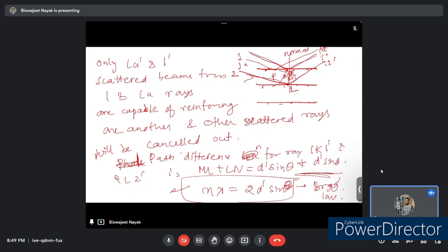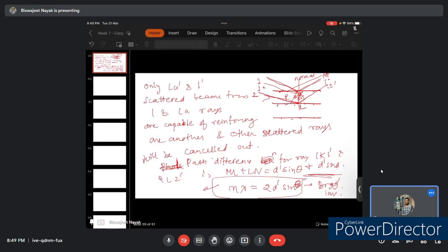Many people confuse and correlate diffraction and reflection together, but there is a fundamental difference between the two. The diffracted beam from a crystal is built up of rays scattered by all the atoms of the crystal which lie in the path of the incident beam. The reflection of visible light takes place in a thin surface layer only.